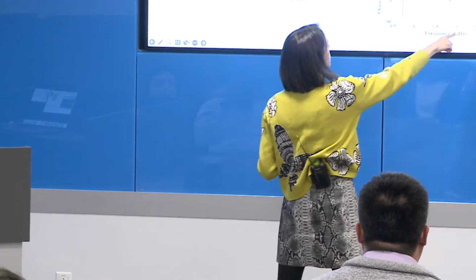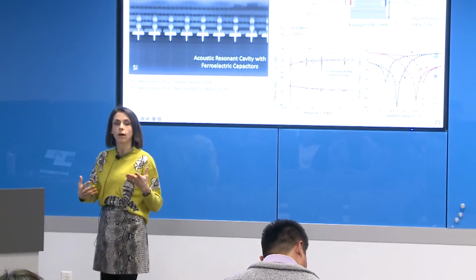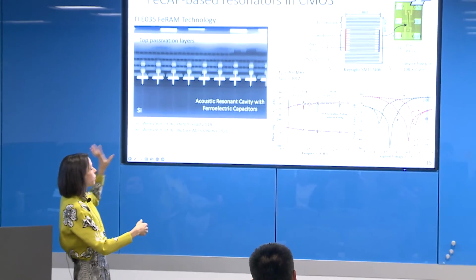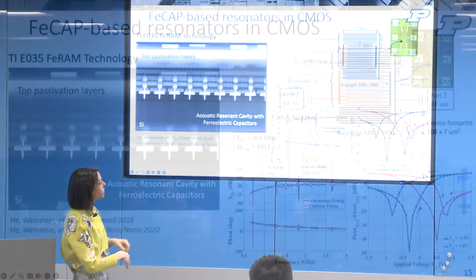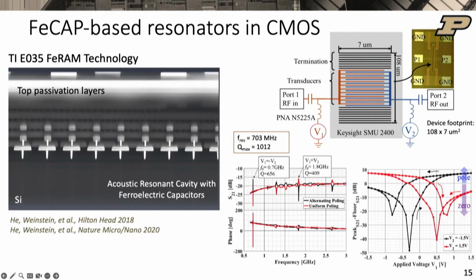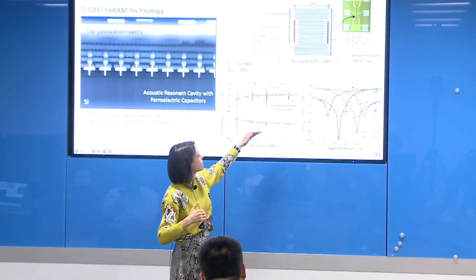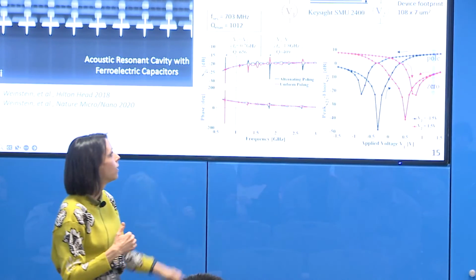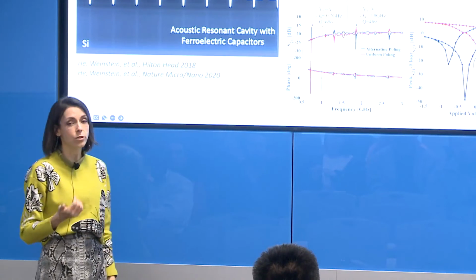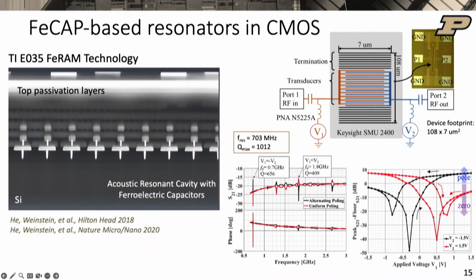If we look at frequency versus the amplitude of vibrations of the structure, this is basically a transfer function from one port to another port across the device. And we were able to demonstrate, with the voltage that's applied, an analog switching of the peak and modify that. We were also able to show frequency shifts in the device corresponding to the mechanical properties of the PZT as you change the bias voltage across it. So you can see the pieces of the puzzle starting to come together on programmability and tunability of these devices.